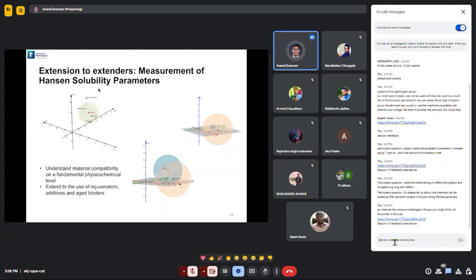this model is we can extend it to different kinds of extenders, such as plastics, SBS, low density polyethylene, and so on. So the way we can do that is that we can model the solubility of bitumen as a sphere, and also we can model the solubility of the additive. So for example, SBS, which is styrene butadiene styrene, is a very well-known modifier for bitumen, and it performs very well. The reason it does that is because bitumen and SBS have very similar solubility parameters. So bitumen and SBS really like each other, and therefore SBS can behave as an added function to bitumen, even giving it more properties such as increased rutting resistance, increased fatigue resistance, and so on.